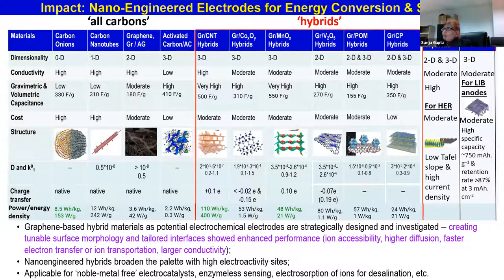I'm going to show you just a couple of slides on the graphene and molybdenum disulfide for the hydrogen evolution reaction. And then in the energy conversion, we designed these lithium ion battery anodes. So the current lithium ion battery anodes are graphite, but with cycling of the lithium ion insertion and deinsertion, intercalation or deintercalation, with time it starts to degrade, and therefore we have to change the battery.